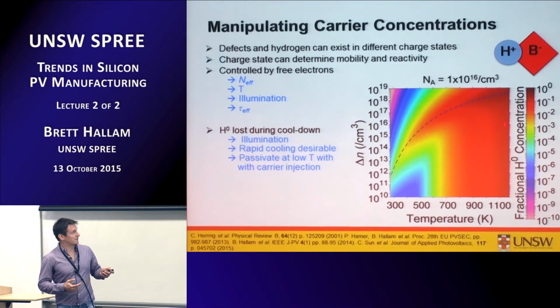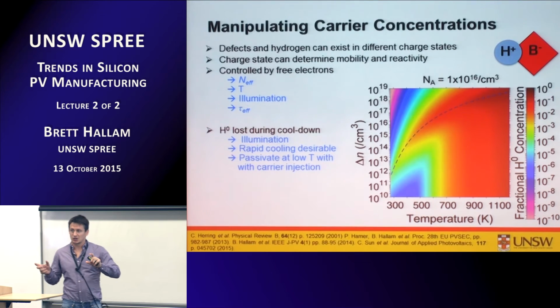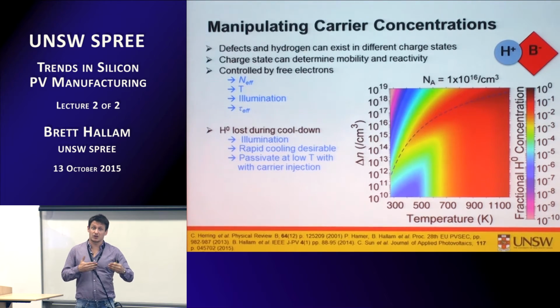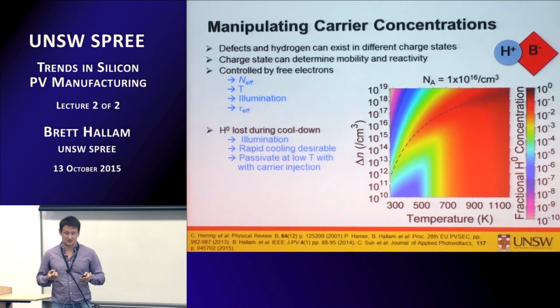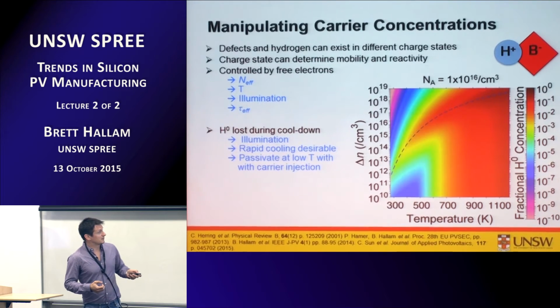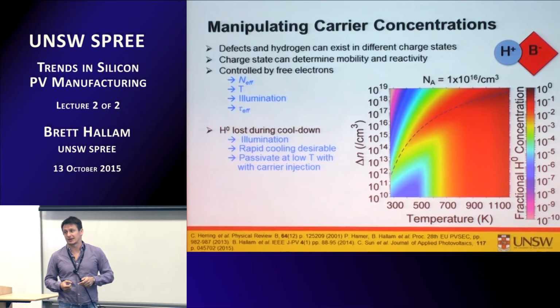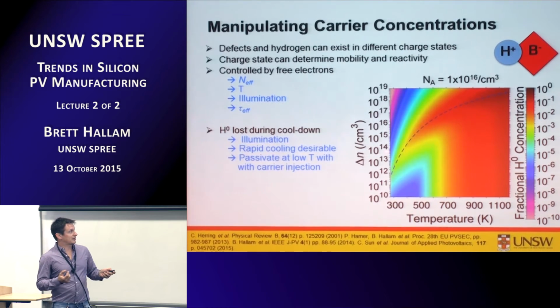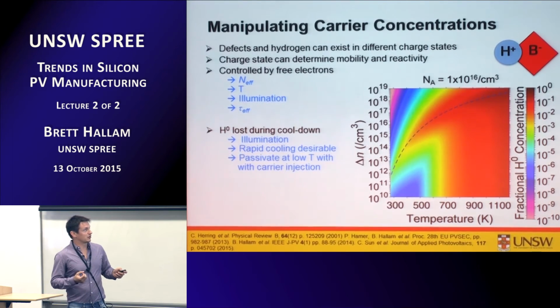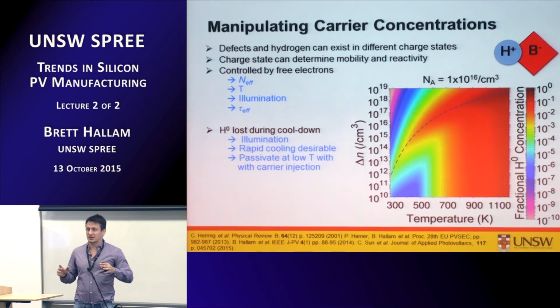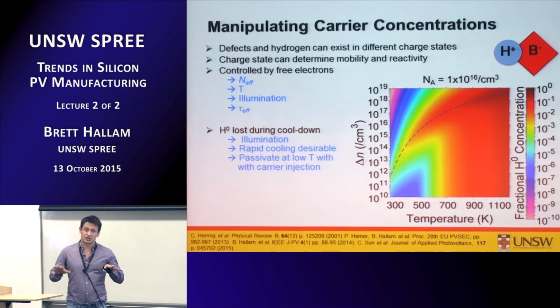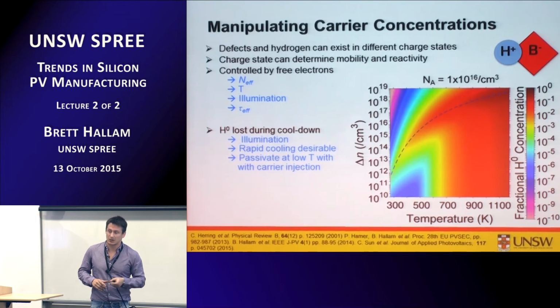So this is a graph that shows theoretical concentrations of hydrogen in a neutral charge state, which has a very, very high mobility, so you can potentially shift to the defect sites very quickly to enable a passivation reaction as a function of temperature and the excess electron concentration in the silicon. And really it's all about the availability of these electrons in determining the charge state of either hydrogen, and it can also change the charge state of the defects as well.